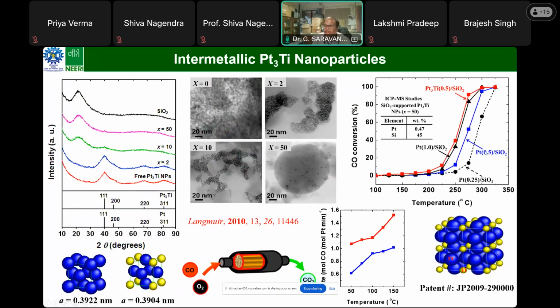Even when we double the amount of platinum, the activity of PtTi is still much better. As I pointed out, we have to minimize the platinum consumption. That's what this intermetallic phase between Pt and Ti achieves, having much better activity than pure platinum, which shows that it addresses our concern. When you compare the working temperature, the intermetallic catalyst PtTi is much better than the others. So when we keep titanium in the lattice of platinum, it changes the electronic structure of platinum, which facilitates CO oxidation.